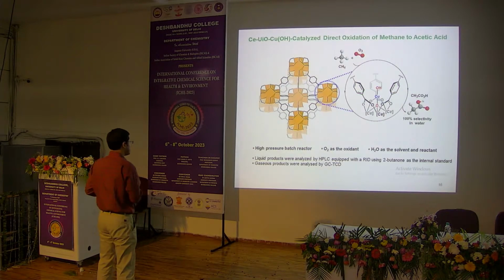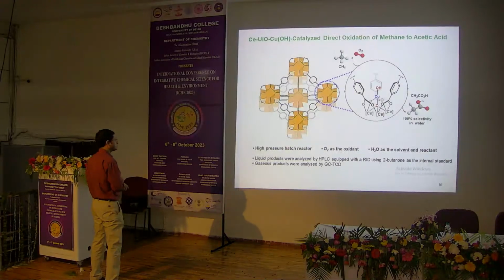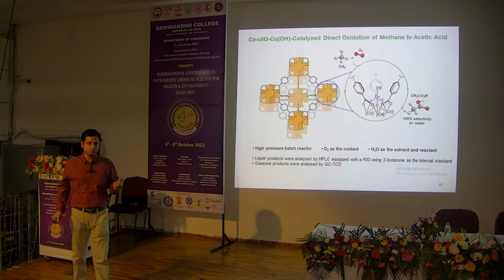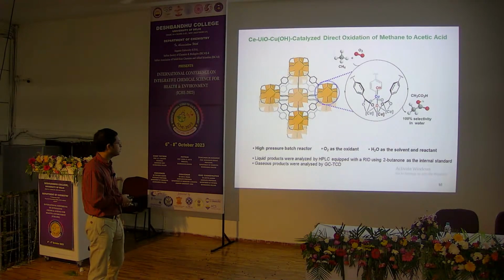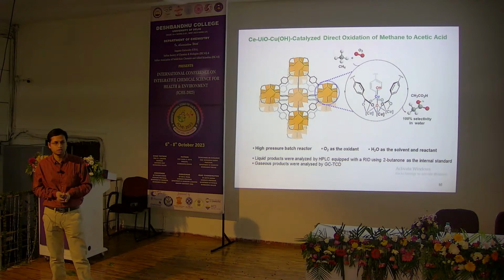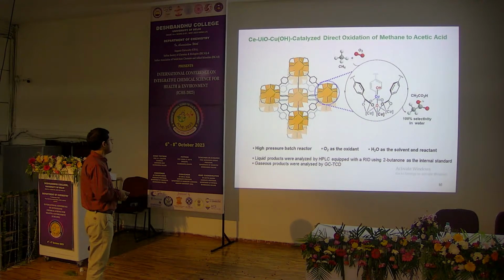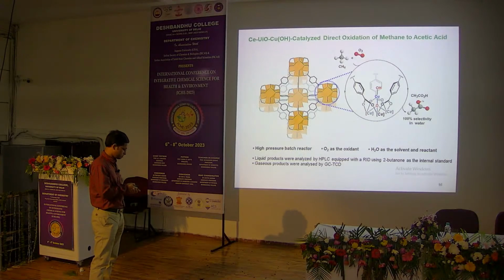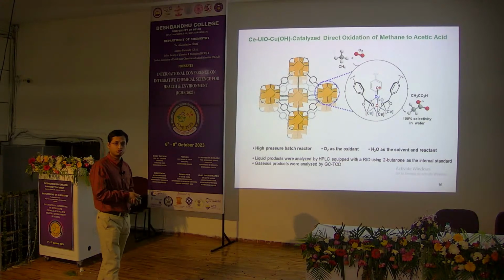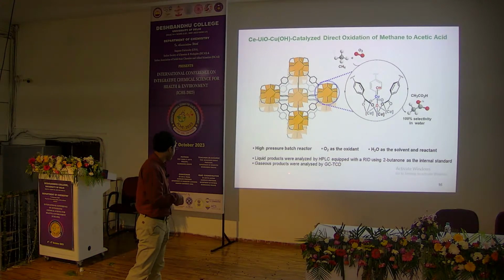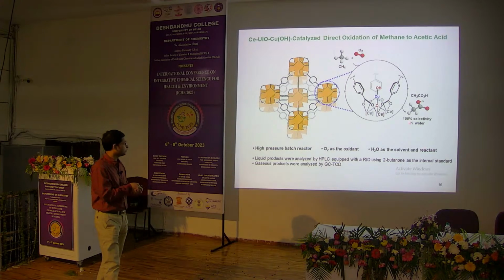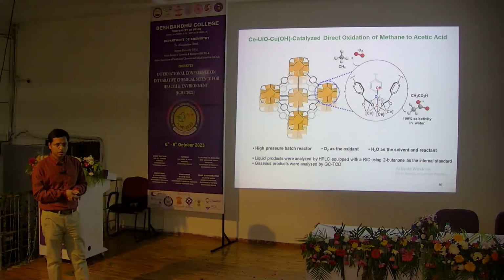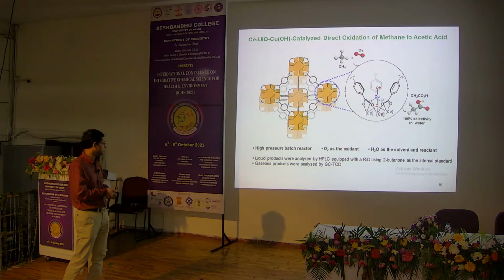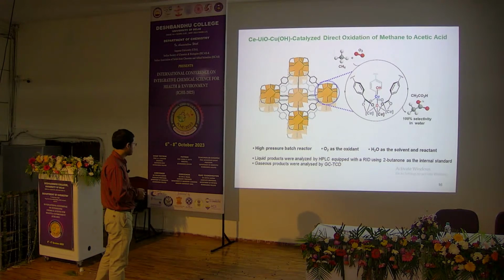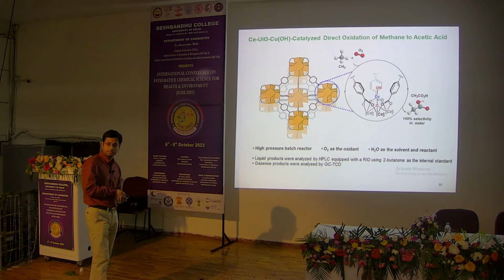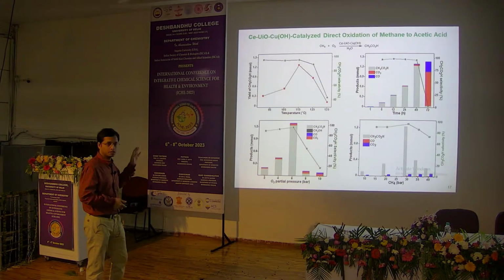This MOF-supported copper hydroxyl material we used for direct oxidation of methane to acetic acid using oxygen as the oxidant. We used a high pressure batch reactor, oxygen as the oxidant, and water as the solvent. The liquid product we analyzed by HPLC as well as RID, and the gaseous product we analyzed by GC-TCD. So this is the optimization.